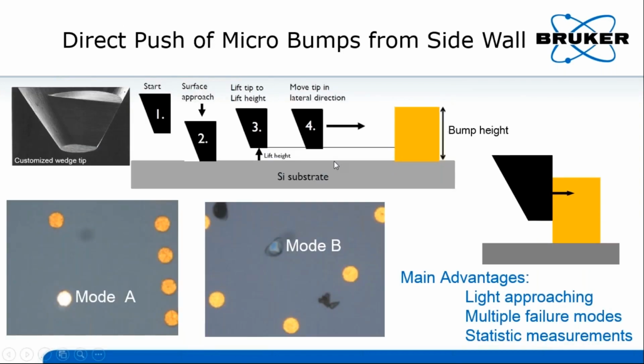Besides the scratch from the cap, another scratch mode that we can perform is a direct push from the side wall using a special wedge tip. Shown here, we can land the probe next to a bump and push it from the side wall. Due to the high sensitivity and the low noise floor, the probe can be landed with very small contact force.